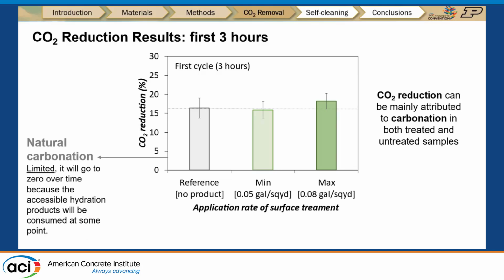So this is our carbon dioxide reduction result for the first cycle. In fact, we can see that there's barely any significant difference between all 3 groups. So the carbon dioxide reduction can mainly be attributed to the carbonation in both treated and untreated samples. However, this carbonation is limited because it's actually consuming the cement hydration products, and after some time it will finally stop.